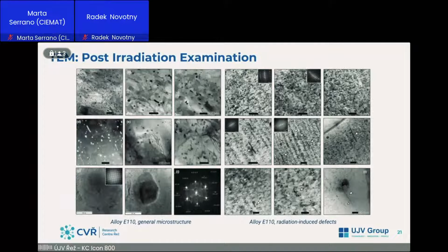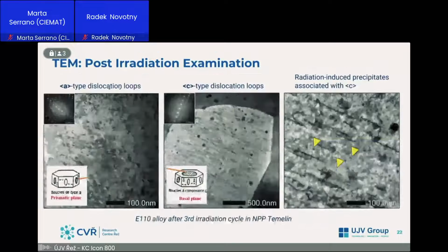Regarding post-irradiation examination, what we evaluate in neutron irradiated materials, we observe the radiation-induced precipitates and different dislocation loops of A and C types. We can observe the hydrides in the microstructure, and we observe the amorphization of previous secondary phase precipitates, which are visible after high neutron fluence. And as well, from the deformed specimens, we describe the deformation mechanisms, which is widely studied.